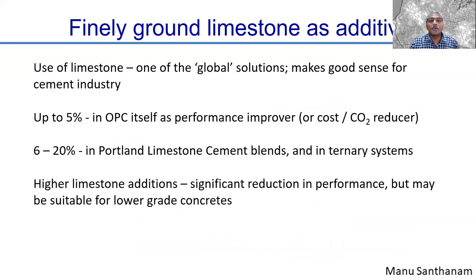So let's now look at finely ground limestone as an additive. As I said, since limestone is available anywhere cement is manufactured, it is certainly one of the global solutions. It obviously makes good sense for the cement industry to be using limestone as an additive in concrete or in the cement itself. For instance, if you look at the Indian specifications for Portland cement or many of the specifications in Europe also, they allow up to 5% replacement of the cement by limestone itself in regular Portland cement. If you buy ordinary Portland cement, you can still have up to 5% of the cement substituted by ground limestone.